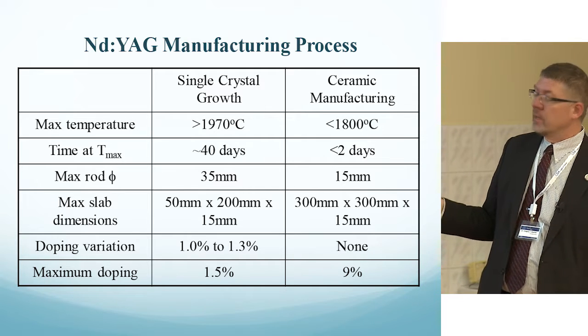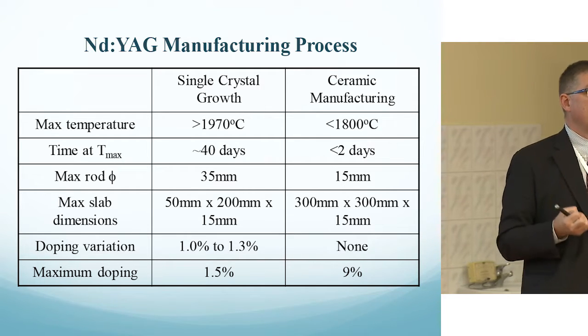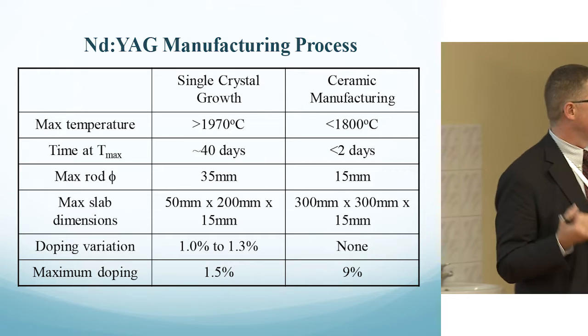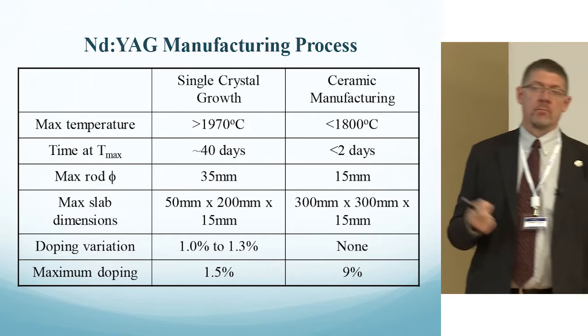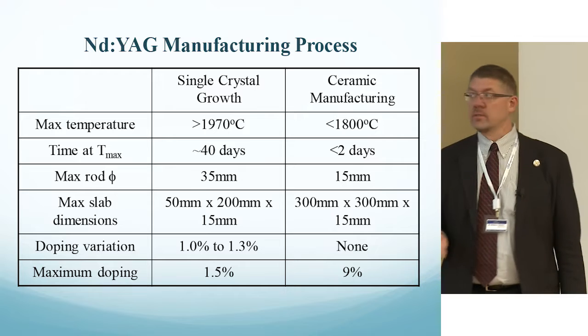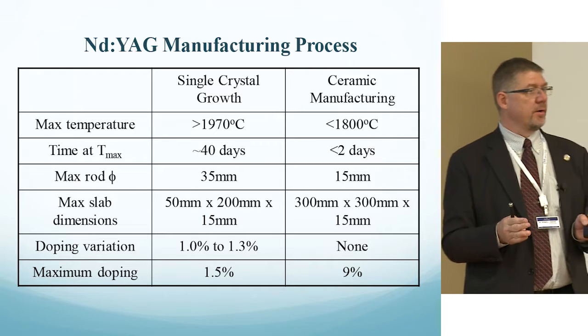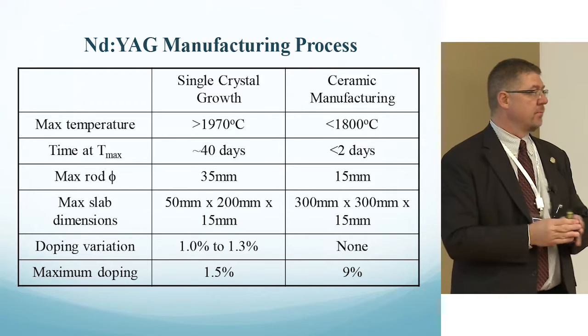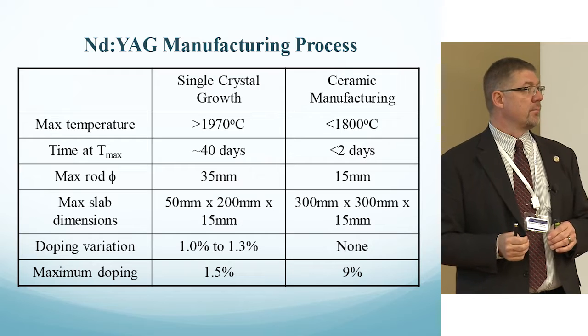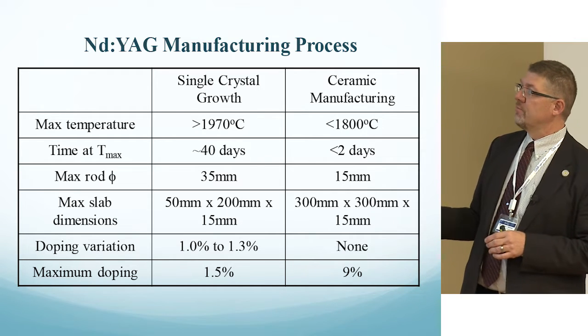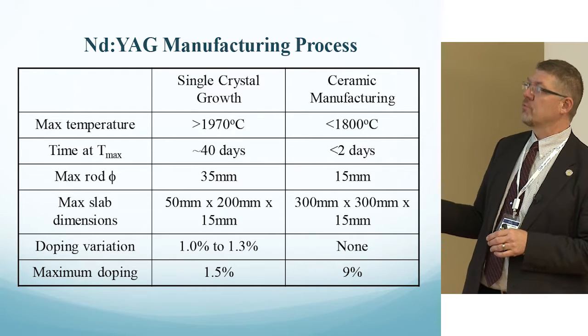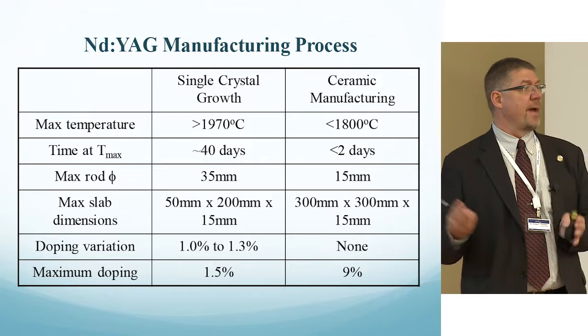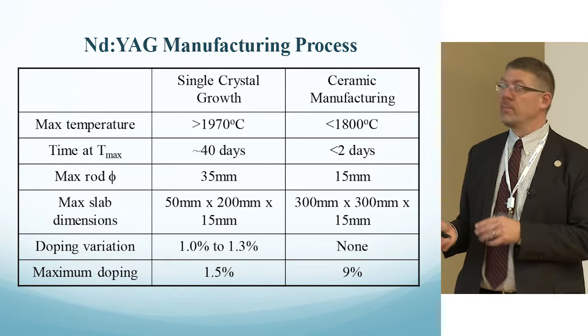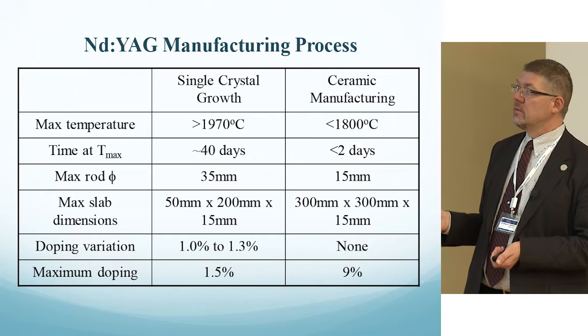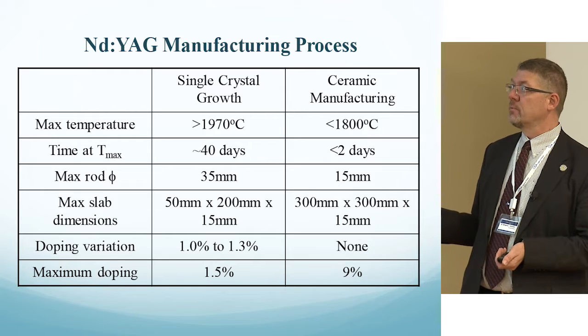Here's where it really starts building in. If you're building lasers where you need extremely high amounts of power, cutting, welding, automobile, military applications, the larger the piece of material, the larger the output power. Gain is a function of unit volume. So here, 50 by 200 by 15, here, 300 by 300 by 15 were the maximum sizes of pure material that could be fabricated. Doping variation was about 30%.